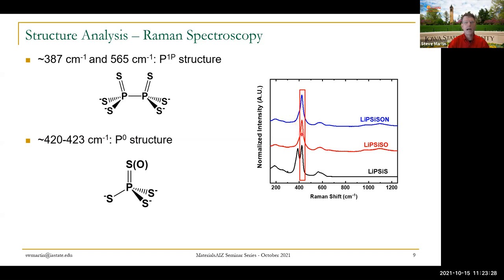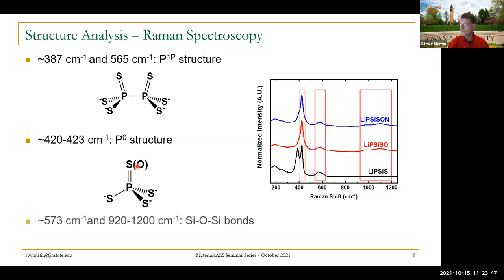We've got a lot of modifier in the glass. If you look real carefully, it's about 70% lithium sulfide, only about 30% of the glass former. And that creates these very highly charged modified structures. What we find is that the oxygen and sulfur substitute on the phosphorus cation. As we add oxygen, as perhaps expected, we see these oxygen peaks come in, and it looks like the silicon takes the sulfur and the phosphorus takes the oxygen, probably in line with the highly negative Gibbs free energy of formation of the silicon.